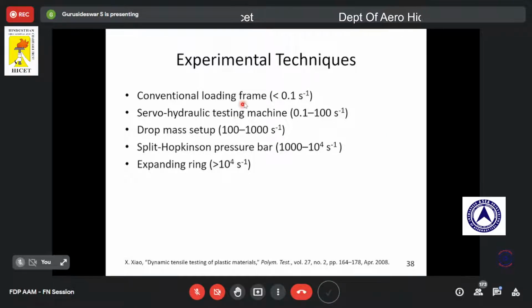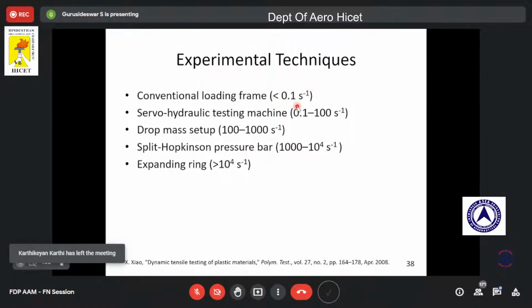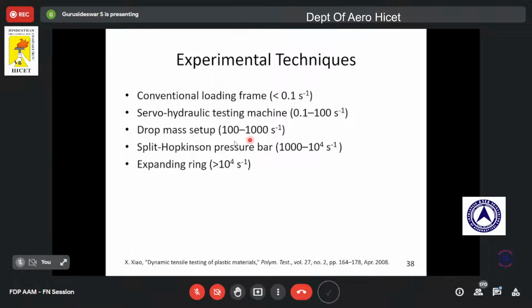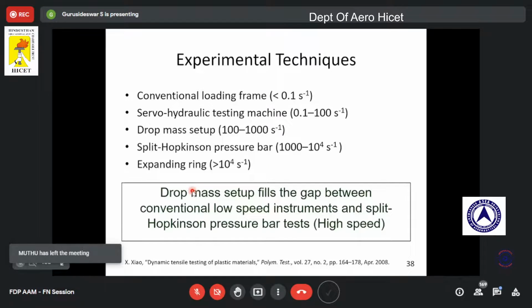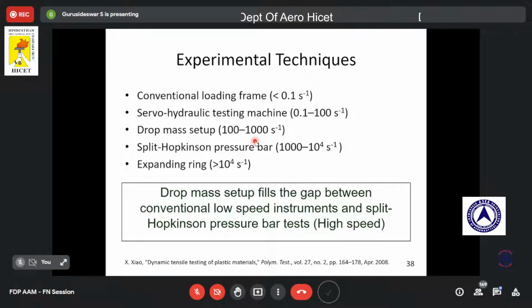So again, there is an important thing we need to discuss. Here I have listed the different techniques for high strain rates. For less than 0.1 per second, we can use a conventional loading frame. For 0.1 to 100 per second, we can go for a servo-hydraulic machine. For 100 to 1000 per second, we can use a drop mass setup. For above 1000 per second, we can use a split Hopkinson pressure bar. For above 10 power 4 per second, we can go for an expanding ring. In this research work, in today's talk, I am going to focus on the drop mass setup. So we have employed a drop mass setup to achieve high strain rates.